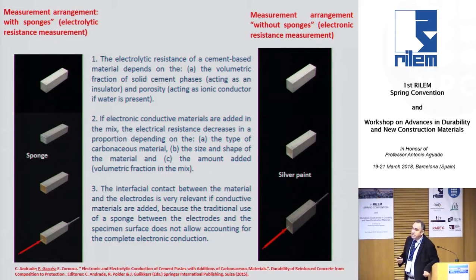In the mix, the electrical resistance decreases in proportion depending on, first, the type of the carbonaceous material, second, the size and the shape of the material, and finally, the amount added, so the volumetric fraction in the mix. And finally, the interface contact between the material and the electrode is very relevant if conductive material is added, because the traditional use of a sponge between the electrode and the specimen surface doesn't allow accounting for the complete electronic conduction.